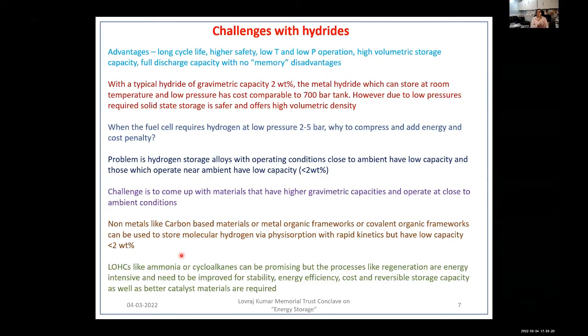Now, if we look at these materials, they have large advantages, because when they are used, they have a long cycle life. You can even charge and discharge these materials with hydrogen for thousands of cycles. They also have better safety, because if there is a leak in such a tank which is storing metal hydride, the reaction of hydrogen coming out of these materials is an endothermic reaction. In that case, the reaction will itself stall, and as such, there won't be a threat of any explosion or a catastrophic event. So these are safe to operate.